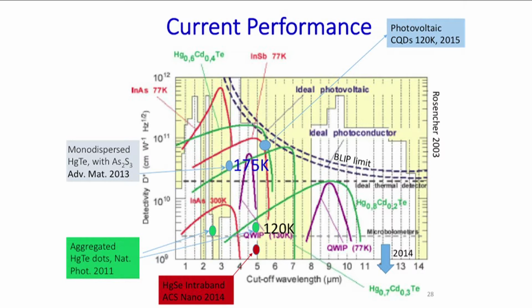And the curves you see here are from the traditional mercury cadmium telluride detectors. They are at the background limit. They're as good as they can be. But they all have to be cooled to liquid nitrogen. And the reason is that as you raise the temperature, you create carriers by thermal excitation. And those carriers give you, of course, a lot of current.